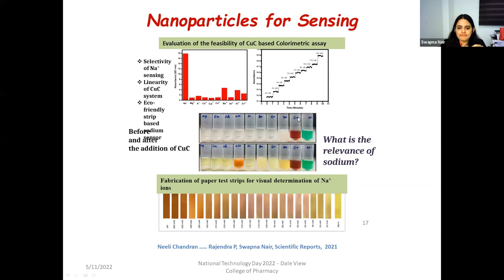It's a medical sensor which can detect sodium in the blood, urine, and sweat. So this got recently published in Scientific Reports, and this shows the selectivity of that particular sensor. It shows high selectivity. We tested in 22 different cationic systems, and we could see that it is responding only to sodium, because while detecting sodium, the interfering species are potassium and calcium, and here we didn't have any such interference. So here it shows high selectivity for sodium.